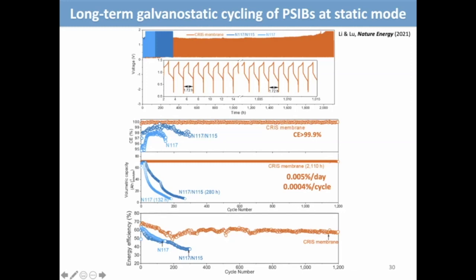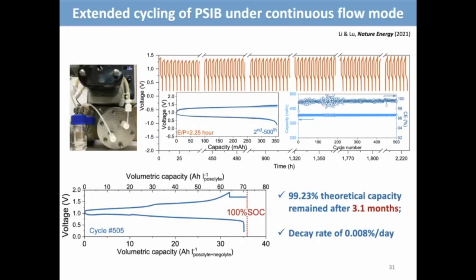And you can actually calculate the final decay rate, which is about 0.005% per day or 0.0004% per cycle. So you can see this is completely different from what polysulfide would have been in the commercial membrane.